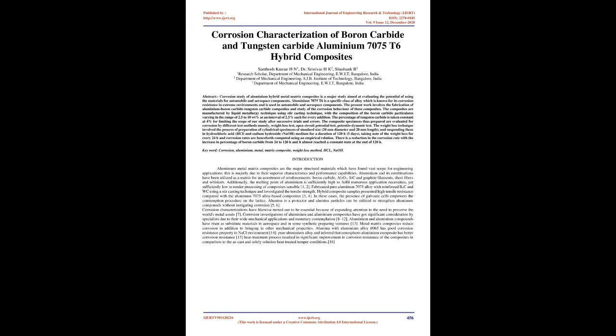The weight loss technique involved the preparation of cylindrical specimens of standard size, 20 mm diameter and 20 mm length, and suspending them in hydrochloric acid, HCl, and sodium hydroxide, NaOH, medium for a duration of 120 H, 5 days, taking note of the weight loss every 24 H, and corrosion rates are then computed using an empirical relation. There is a reduction in the corrosion rate with the increase in percentage of boron carbide from 24 to 120 H, and it almost reached a constant state at the end of 120 H. Keywords: corrosion, aluminium, metal matrix composite, weight loss method, HCl, NaOH.